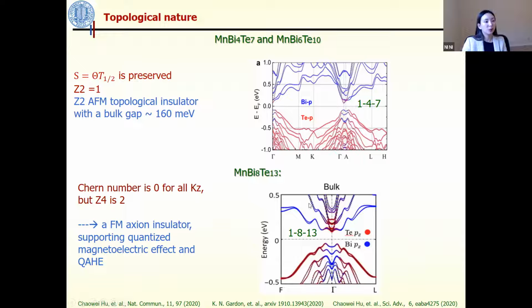And for manganese bismuth telluride 1-8-13, because it's ferromagnetic, the time reversal symmetry was completely broken. So the Z2 invariant is no longer well defined, but the Z4 invariant, which is well defined here, equals 2. If Z4 is odd, it indicates a Weyl semimetal phase. And if Z4 is equal to 2, it actually corresponds to an insulator phase where a quantized topological magnetoelectric effect can actually occur. So 1-8-13 was identified as a ferromagnetic axion insulator by the DFT calculation.